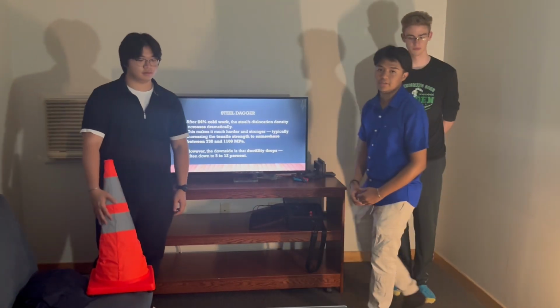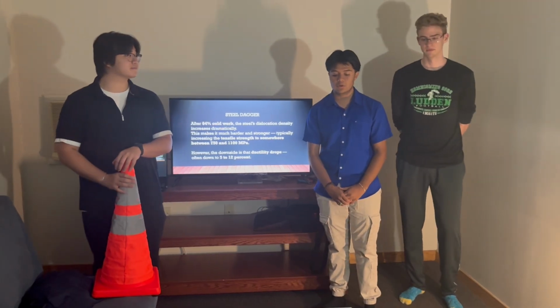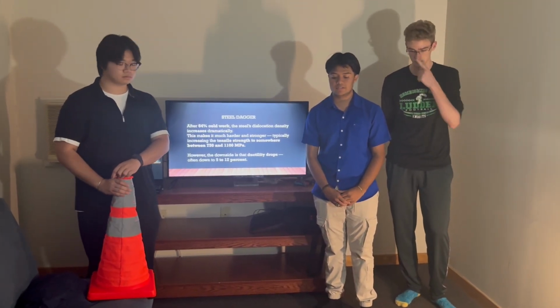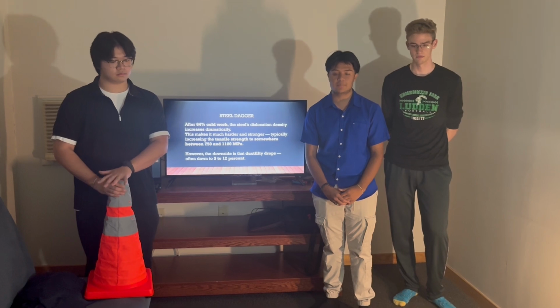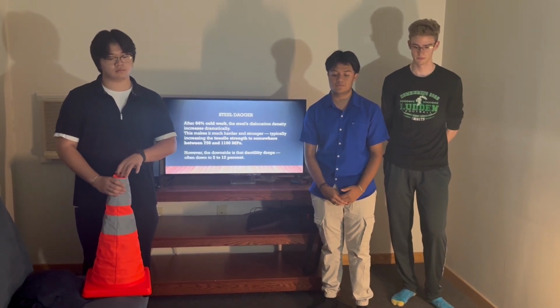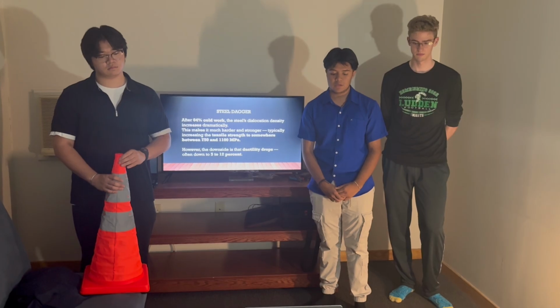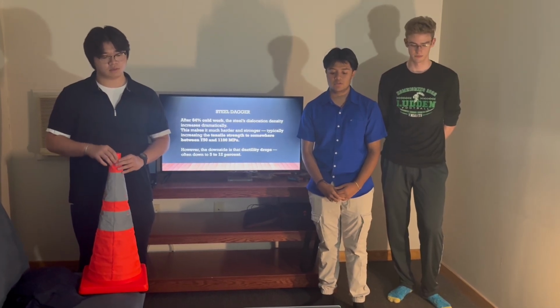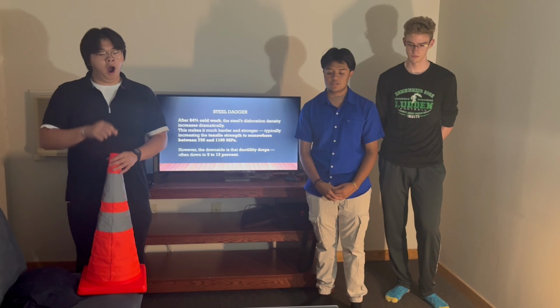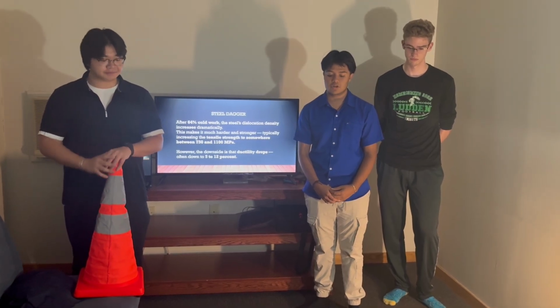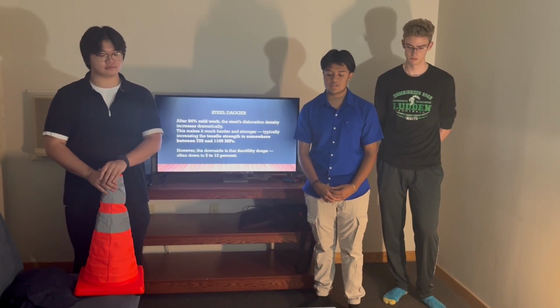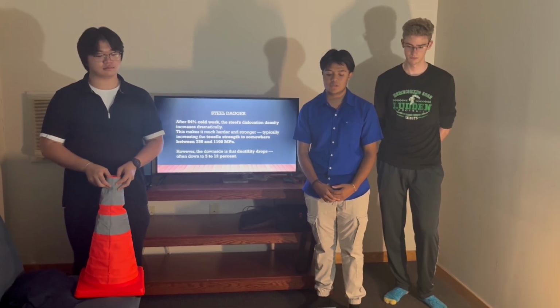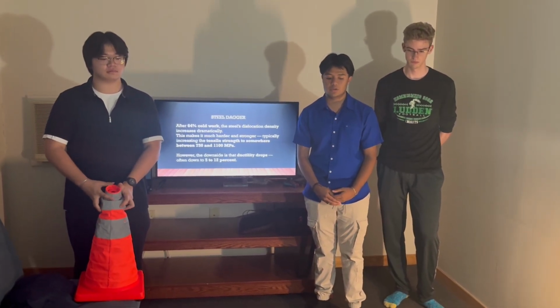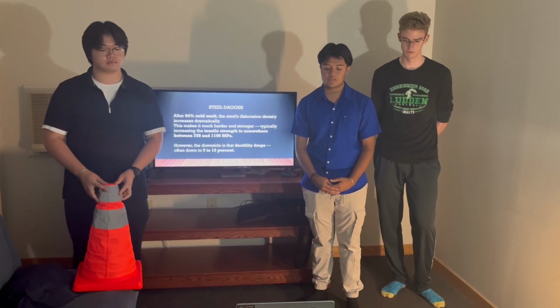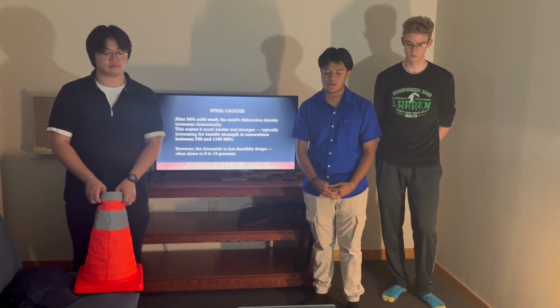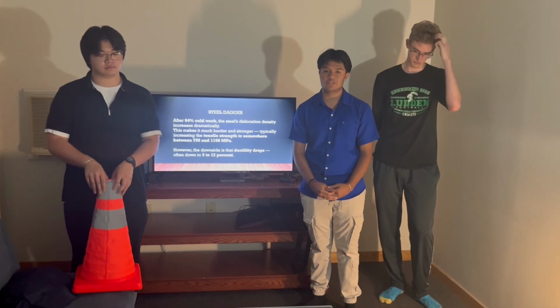Now let's talk about the steel dagger first. In its annealed or normalized condition, many steels have a tensile strength between 400 and 600 megapascal, and an elongation between 15 and 30%. After 84% of cold work, the steel's dislocation density increases dramatically. This makes it much harder and stronger, typically increasing the tensile strength to somewhere between 750 and 1100 megapascal. However, the downside is that ductility drops, often down to 5 to 12%.